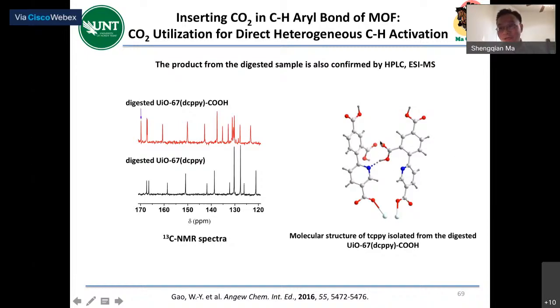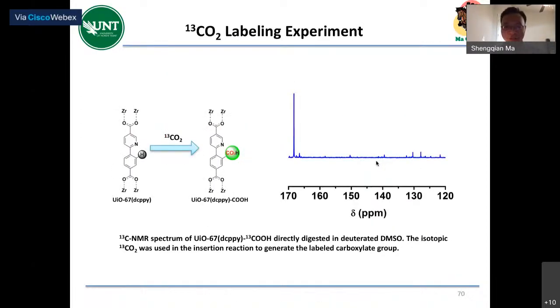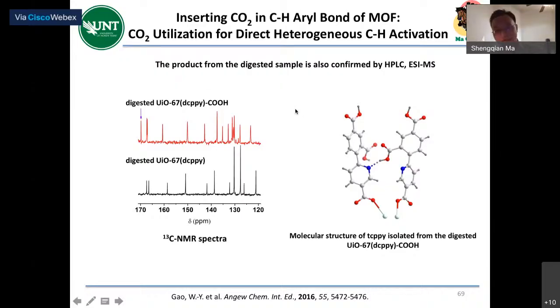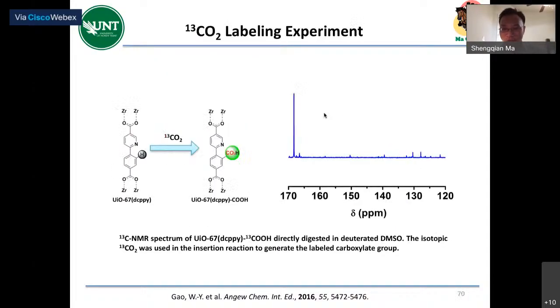And if you directly use the ligand, you're not going to get the UiO-67 because they form hydrogen bonding. It's going to disrupt the equilibrium for the MOF synthesis. Right? So even with all these results, I think that's a few years ago, the reviewers didn't believe we made it. Okay, that's probably several years ago. It's too new and too hard. And then, of course, as a standard, we need to do the carbon-13 labeling study. Exactly, you can see the peak, right, compared with the previous one. It's much stronger. Very obvious. It's from carbon. This carboxylate carbon is inserted from CO2.